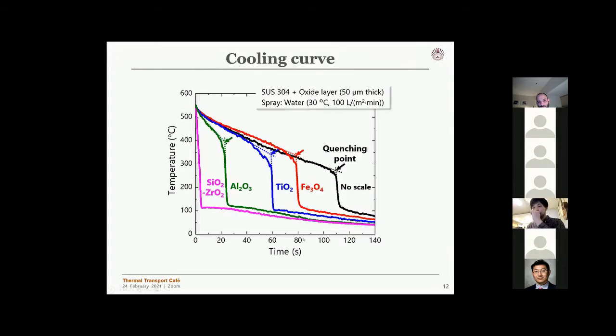This is the typical cooling curve we've obtained, showing the temperature at the interface between the oxide layer and the stainless steel plate as a function of time. We have a reference line here, which is the no-scale case with no oxide layer—this is the basic cooling curve for the stainless steel plate.